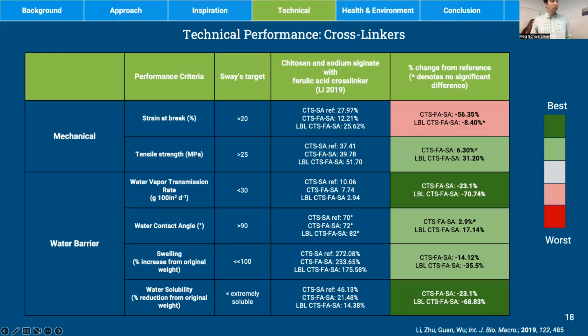Some things to note here is that we see water barrier metrics are vastly improved when a layer-by-layer approach is utilized. This is thought to occur, and I should say the same occurs for tensile strength. This is thought to occur as the layer-by-layer approach allows a greater surface contact between the two layers, resulting in a denser structure. Furthermore, the same can be said for utilization of ferulic acid.